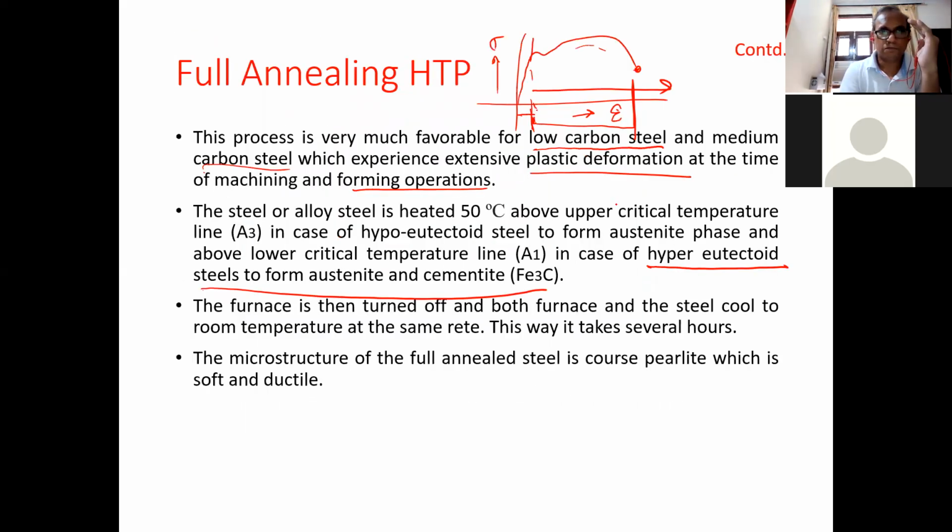The furnace, अच्छा, and what is another thing? ये करने के बाद में, heat करने के बाद, the furnace is then turned off and both furnace and the steel cool to room temperature at the same rate. फर्नेस के अंदर ही आप फर्नेस को बंद कर देंगे, ऑफ कर देंगे और उसको ठंडा होने देंगे. The microstructure of the full annealed steel is coarse pearlite, which is soft and ductile. Okay, so this is another point to remember.